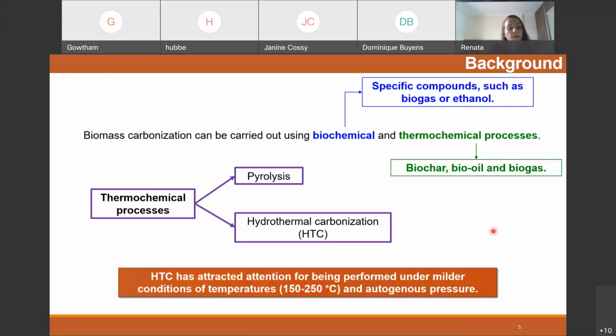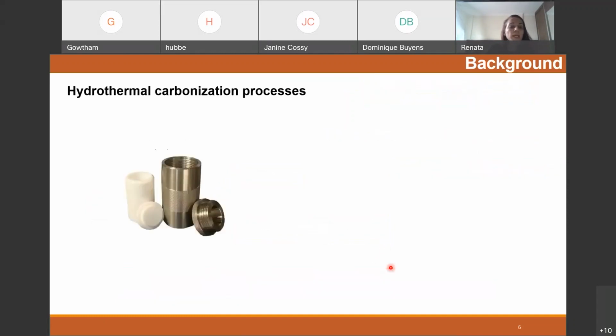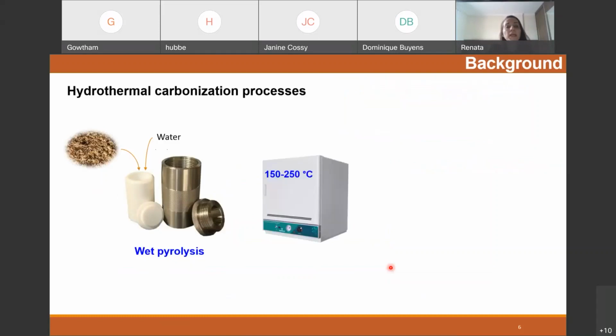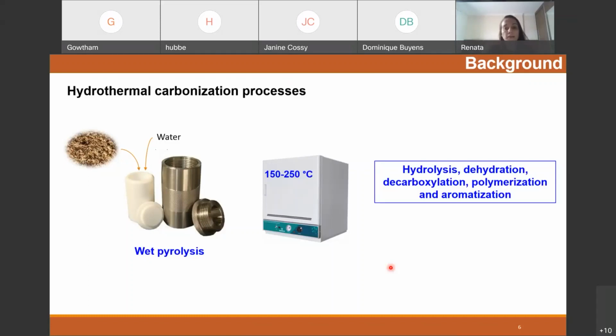I highlight hydrothermal carbonization, because this process can be performed under mild conditions of temperature and autogenous pressure. In the carbonization process, the biomass is added to an autoclave plus water. This process is called wet pyrolysis because it occurs in the presence of water. The system is placed in a stove at mild temperature, and many kinds of reactions occur in the process, such as hydrolysis, dehydration, decarboxylation, polymerization, and aromatization.